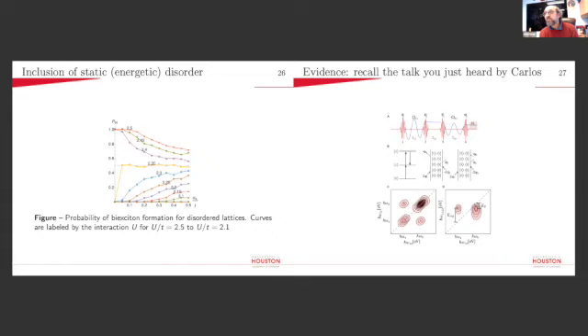But then the other question is the effect of the static, energetic disorder, because all of these conjugated polymer systems are in a noisy, static environment. There are fluctuations and stacking differences and all sorts of stuff going on. So one of the questions we were interested in is how stable this biexciton is to simple energetic disorder of the system. What I show on the curves is basically the increasing of the interaction from very strongly interacting to very weakly interacting for a given model of the system.